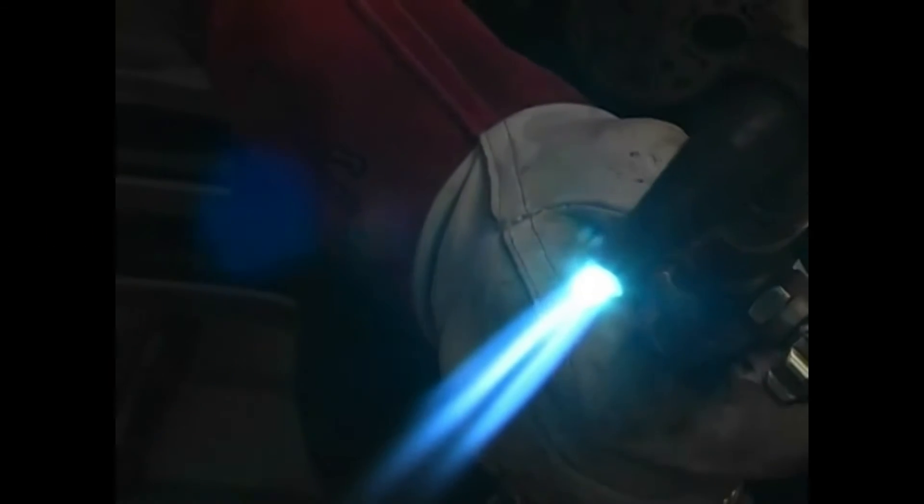Key characteristics of an oxidizing flame are a small, sharp, more pointed looking cone flame at the base of a shorter feather flame. An oxidizing flame will have a distinct roar.